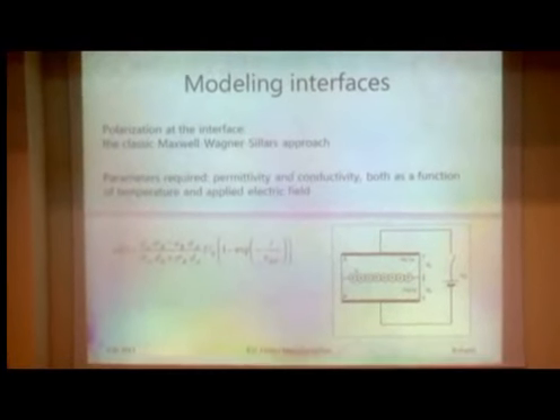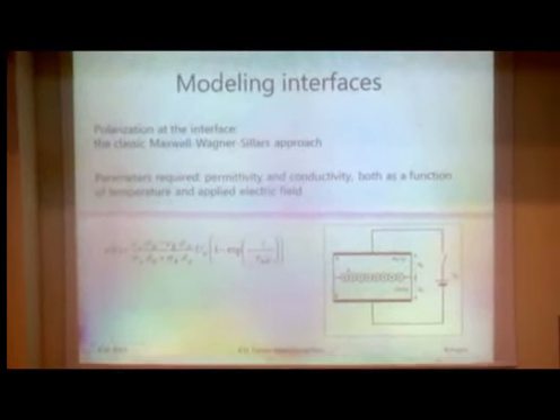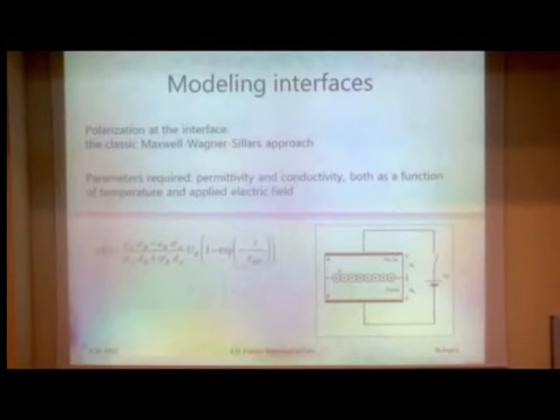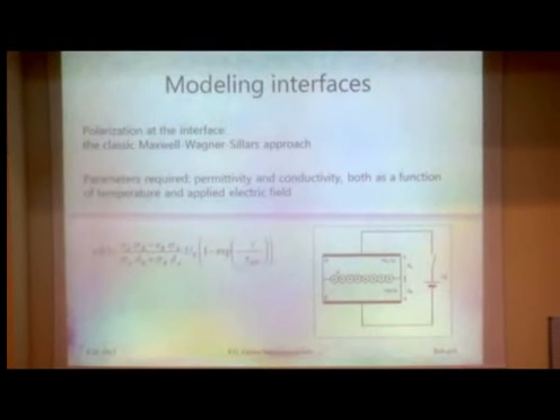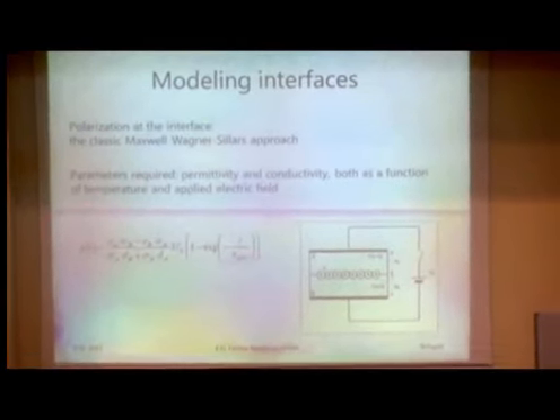Now I want to start very simple. Forgive me for that, because I like to first look at things with very simple models. If we have a system consisting of two media, there's this classic theory by Maxwell, Wagner and Sillars, which shows you how you can calculate the charging of the interface if you have access to the macroscopic parameters, conductivity and permittivity. Very basic, very straightforward, but very easy to check. And then you get this exponential growth of the surface charge at the interface between two dielectrics.